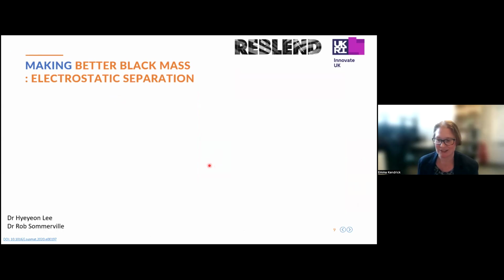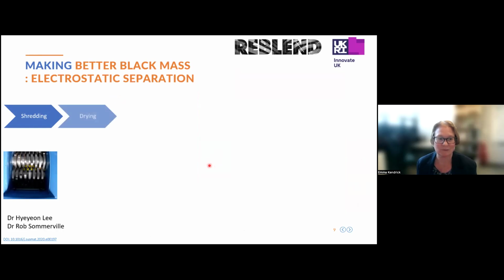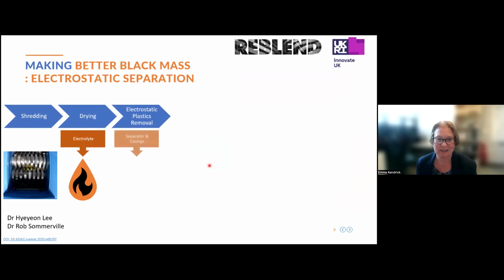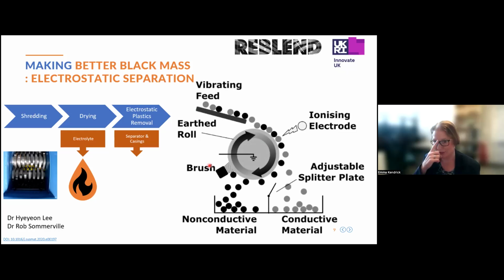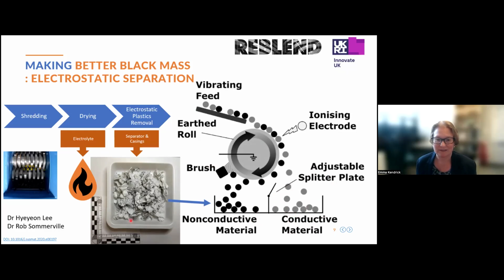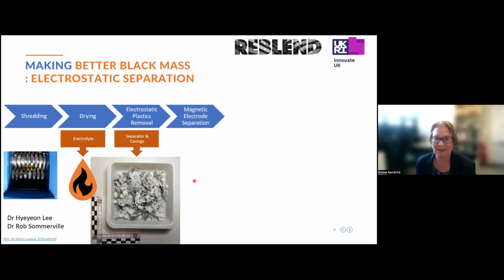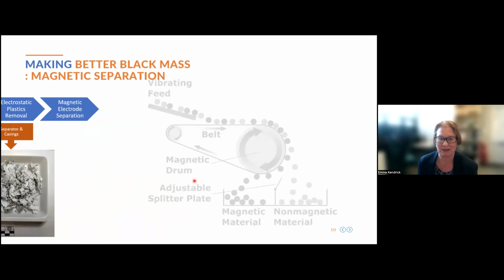And so what we have done is look at the disassembly and the shredding process. First of all, we'll take the shredding process. We go through a drying step to recover the electrolyte, and then an electrostatic process from the shred, which then ionizes the feedstock. The separator sticks to a drum, and we can just brush off the separator as a non-conductive material, and then keep the conductive material separate. What we do with this, and this is the example of the separator that we get from this process, there's a little bit of contamination. It's rather low in mass because separator is low in mass, but we can separate it at about 97% efficiency from this method. After the electrostatic process, we take it through a magnetic electrode separation process.